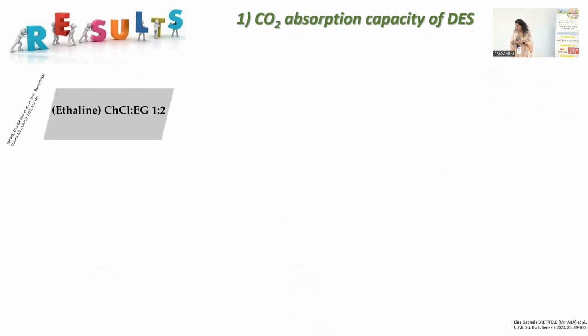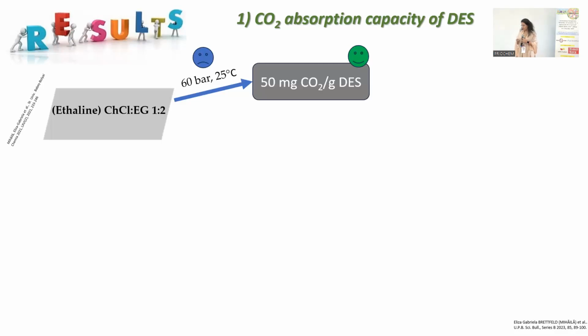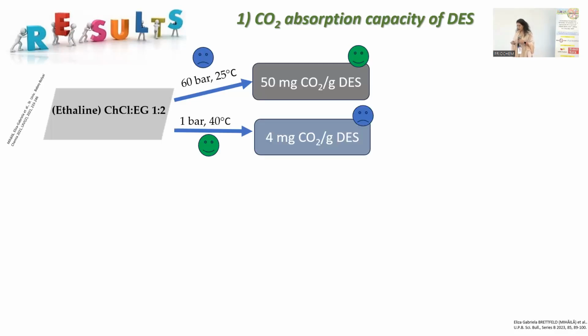Results, the first part of the results. As I told before, for the ethylene glycol solvent we tried two main working parameters. With high pressure and room temperature, we had an interesting result, and the greener working parameters, with a slight increase of temperature but atmospheric pressure. An industry man would not like the 60 bars pressure. The results on the greener methods weren't so attractive.